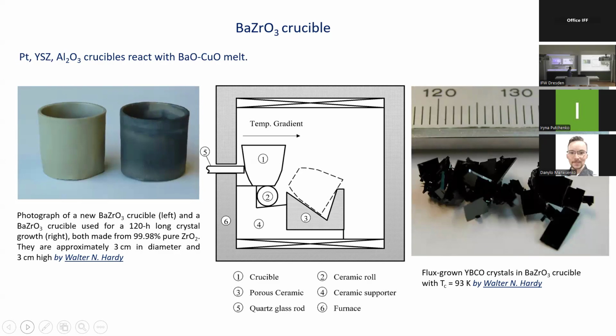physical properties. Zirconium doesn't enter the crystal structure, although due to the very strong reaction with the melt, we are not able to prepare large size crystals. And the most inert material is barium zirconium oxide. These crucibles are commercially available on the market, although their quality and reliability is not really high. They are often cracked during the growth, and they are relatively small. So the production is still challenging for companies.